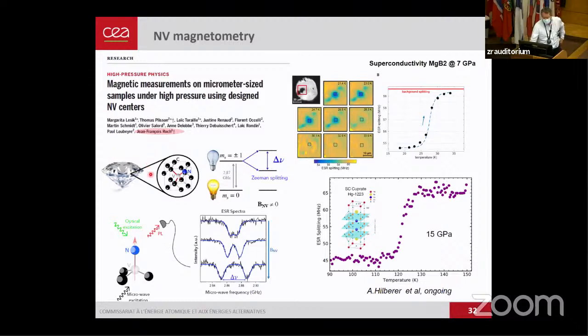So NV is a defect in the diamond. It's a 2-level system, and the photoluminescence is dependent on the state of the spin of this level. And since this one is brighter, you can polarize under illumination one of the levels, 0. And so then, since you have polarized your system with photoluminescence, if you send a microwave and you scan the microwave, you can really probe where there is a transition resonance and probe this level.